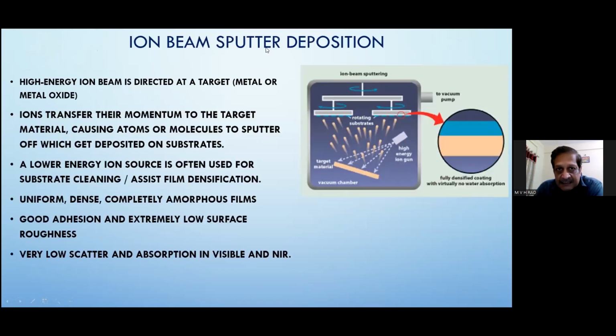Okay. In the case of ion beam sputtering, this also I already explained. There is a target and an ion source, mostly argon is used. Argon is ionized inside a chamber. Plasma is created inside the ion source and then accelerated through a grid and comes out with about 500 to 1000 electron volts energy. Those energetic argon ions hit the target and knock off the atoms. These atoms come out in the form of molecules and atoms, in the form of vapor, and get